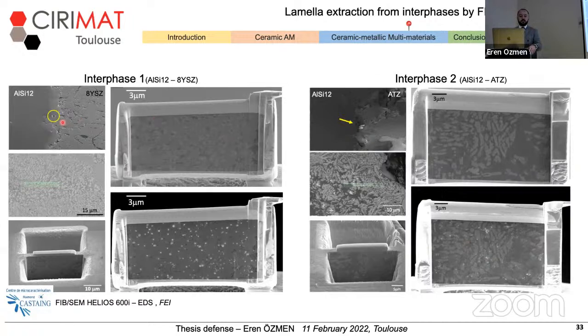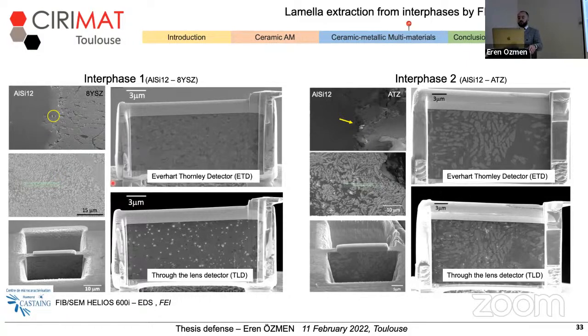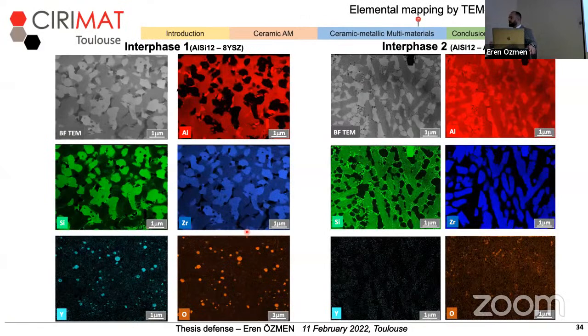As we see with the areas circled with yellow and arrowed, from the interfaces, we removed a lamella with a certain thickness with the help of FIB technology. And when we observe the lamellas with two different detectors, one only a secondary electron detector, and the other a detector that combines backscattered electron and secondary electron detectors, we see that for both lamellas, rounded shaped formations appear in the lamella. So as this lamella exactly corresponds to the interface, I wanted to perform another elemental mapping at high magnification.